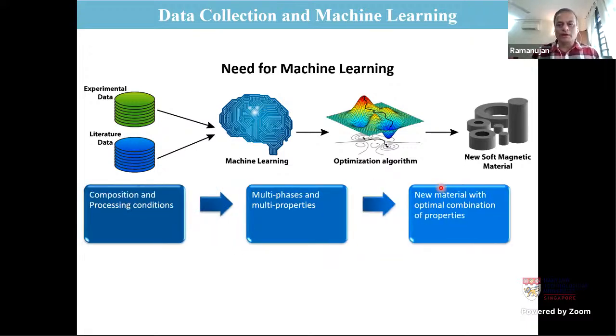So basically, we are able to incorporate not only composition in our data collection, but we can also introduce processing conditions, which is of great practical interest, especially for the case of magnetic materials. The properties tend to be very sensitive to the heat treatment or the method by which they are made, whether it's casting or forging. So these look like engineering details, but in reality, to produce bulk materials, you do need to identify these processing conditions.